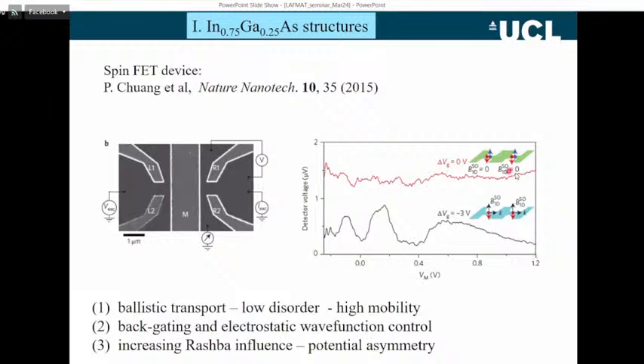However, when we've got the red curve here, that's set up so there's no spin. We haven't removed the degeneracy between the spins. So we have both spins that rotate round. So there's no spin selectivity. However, when we apply an asymmetric gate bias to the left-hand side, that's in the lower diagram, then we see this: we can just pick out one spin and rotate the one spin around.